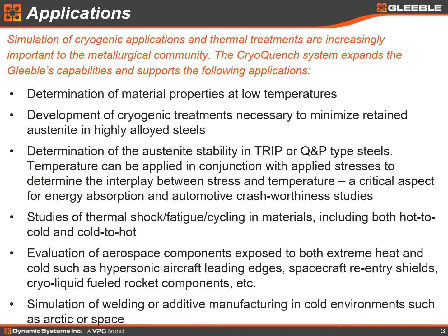Some of the other applications that we envision for cryogenic quenching is the determination of material properties at low temperatures, the development of cryogenic treatments to manage retained austenite in highly alloyed tool steels, the determination of austenite stability in TRIP or quench and partition type retained austenite steels, where the austenite stability is not only going to be critical for the initial forming of those steels, but also for any potential crash worthiness in an automotive application that those steels may be applied to. The studies of thermal fatigue and shock cycling of materials is also going to be quite critical, and simulation of welding or additive manufacturing in very cold environments such as Arctic or space.